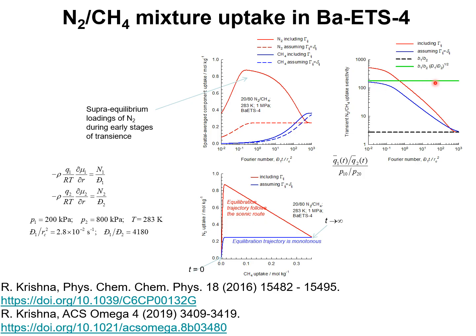corresponds to this value of kinetic selectivity during the early stages of transience for a model in which the thermodynamic coupling effects are ignored. And therefore, this concept of the kinetic selectivity and this formula that is shown here is not of general applicability, and this is a cautionary note to researchers who tend to base their calculations only on this simplified formula.